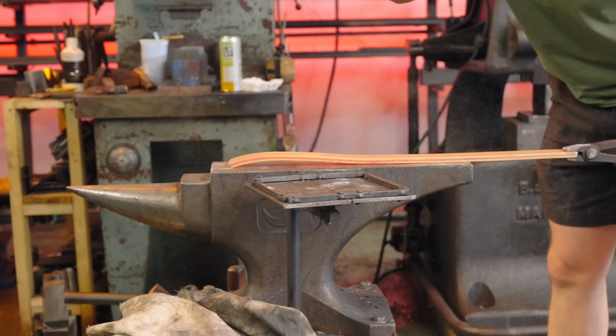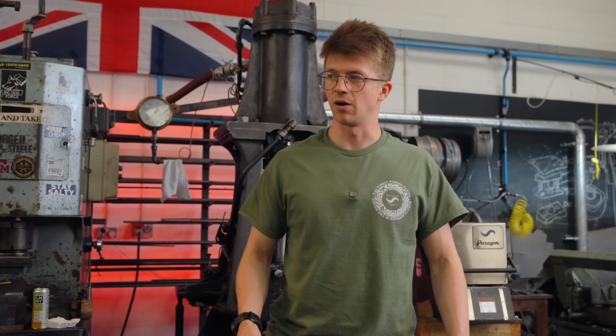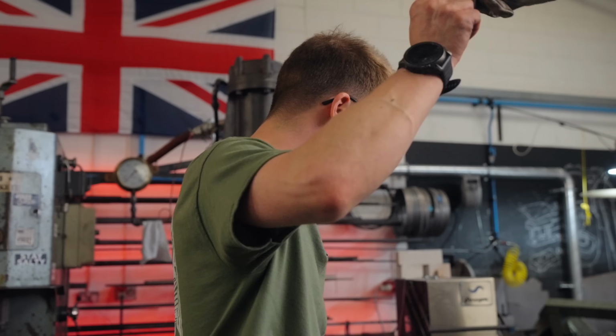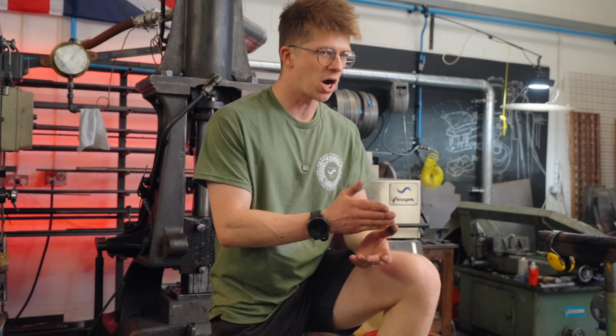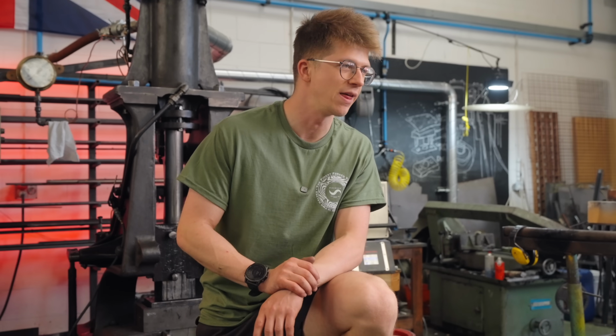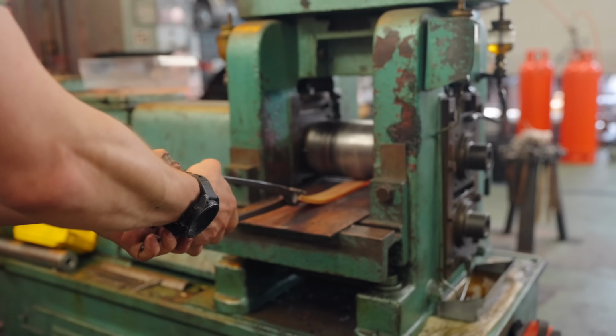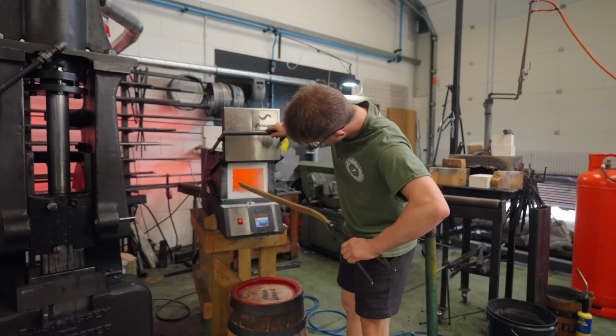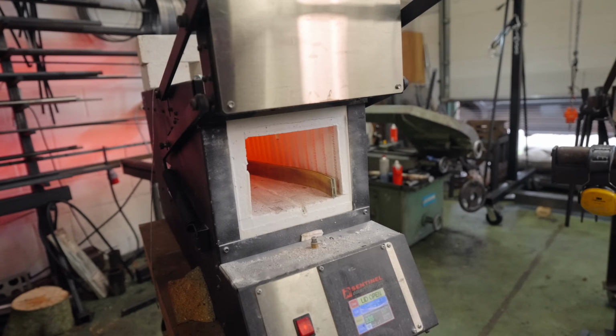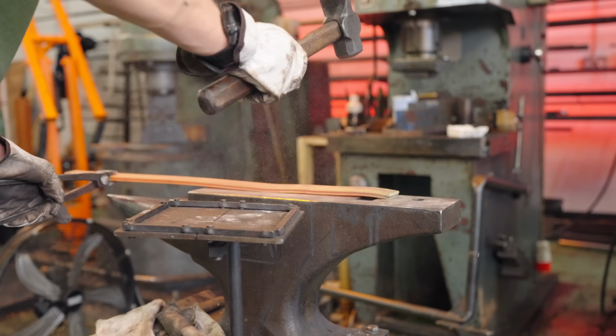Woo! Don't break. Only get about one more heat out of it before it's too long. Hard to make good videos when you're sad. Yeah, it's gonna be a real problem here. Because if you start saying, oh, I'm gonna make a titanium Damascus katana, and then you can't make the titanium Damascus katana, that's some real noob behavior there. Whoa, that got a bit bendy. Will it fit though? Oh gosh, don't know if that counts as fitting.